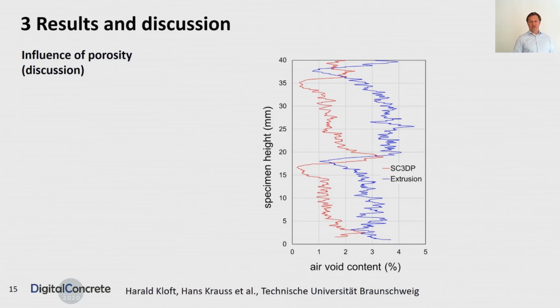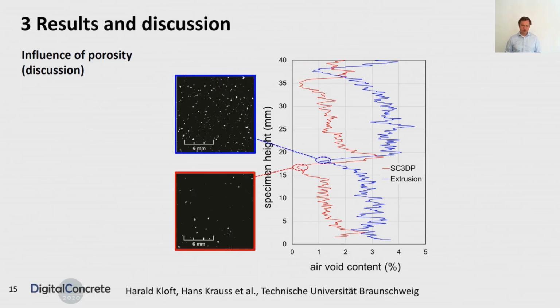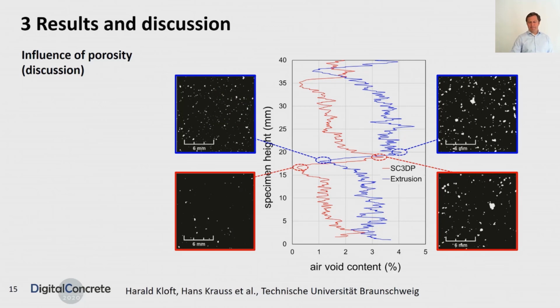What we can see is that we generally have a lower level of air void content in case of sprayed specimens as compared with extruded specimens. But in this region, where we have the interface, we see two characteristic points. First, we see in both cases a porosity minimum, which is very distinct, and you see here the evidence from computer tomography in form of false color images. It's very low porosity here in case of shotcrete 3D printing and slightly higher but homogeneously distributed porosity in case of extruded specimens. Whereas above the interface we have a zone of higher porosity, and you can see this clearly by the images.